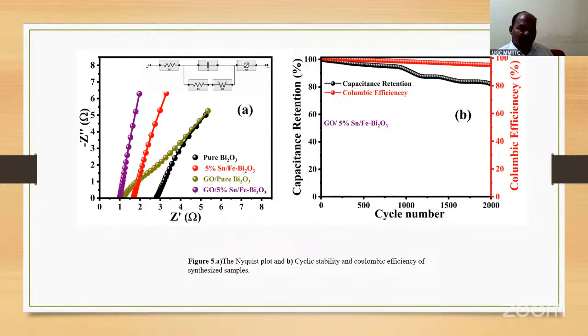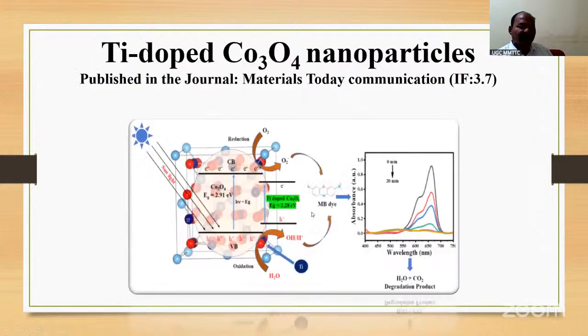Now this plot shows cyclic stability and the Nyquist plot, and the Coulombic efficiency of the synthesized samples. Capacitance retention and Coulombic efficiency we have also calculated here. Now titanium doped cobalt oxide nanoparticles: this work was also published in Materials Today Communications, impact factor 3.7, and these are Scopus indexed papers.